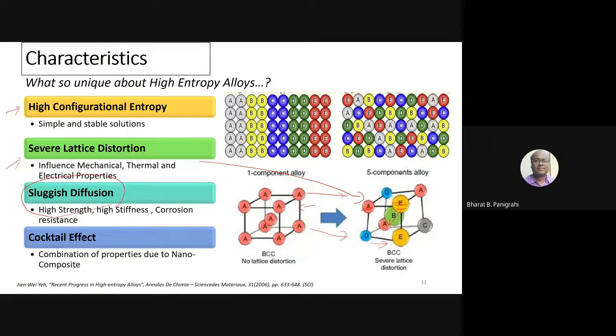The next one is called sluggish diffusion. This particular group is a little controversial. People have a lot of different opinions when it comes to diffusion. However, it shows sluggish diffusion. The reason people describe it as sluggish diffusion is that whenever you heat a material at high temperature, normally you see huge grain growth. All normal steels, alloys, titanium alloy, it doesn't matter. At high temperature, you will see huge grain growth. But in high entropy alloy, you will not see grain growth, or you will see extremely slow grain growth.